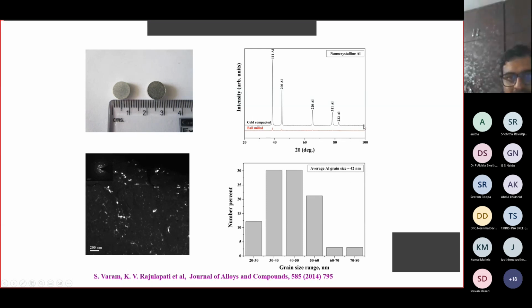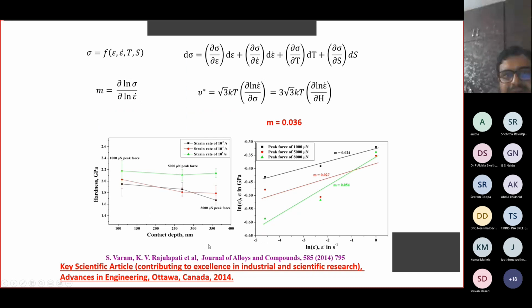And here you have an X-ray diffractogram that shows that you have pure aluminum. When we look at the peak broadening analysis using X-ray line profiles, it shows that they are all nanocrystals, and the grain size that we estimated using the Scherrer equation from the X-ray line profile analysis closely matches the grain size that we obtained from the TEM dark field image analysis. The inset here is also a diffraction pattern that shows that it's pure aluminum. And we published this work sometime in 2014 in the Journal of Alloys and Compounds.